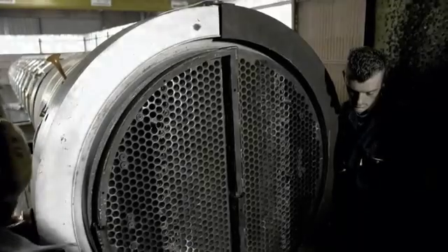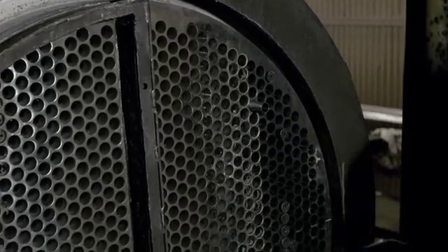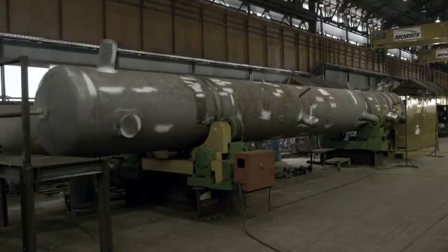Although the explosion generates heat in excess of 2000 degrees Celsius, this is irrelevant as the entire explosion is complete within milliseconds. There is thus no stress relieving required by normal thermal welding methods. The explosive welds are also unaffected by thermal cycling when in operation, making the process ideally suited for heat exchangers like high-pressure heaters.